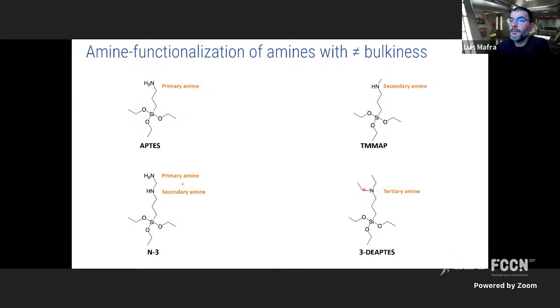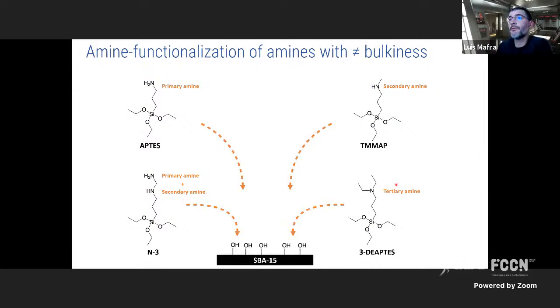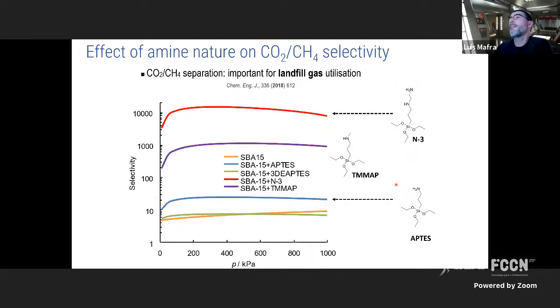It's so hindered, chemically hindered, that it's not able to really bond CO2. And this is well known already in literature. So let's see what happens. So we grafted it on benchmark silica, SBA-15. We were not worried really to use top-notch materials. The group is not so much concerned in using the best materials available. We just want a material that works well, which has been well characterized, because we want to chase these species that nobody knows about, or very few people know about.